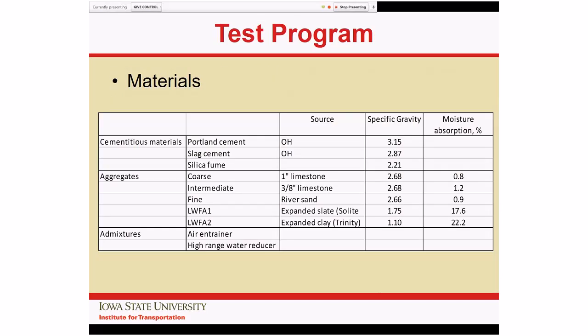All right, so we ran a fairly rigorous program through the lab. We played with Portland cement that we obtained from Ohio and a slag cement from Ohio. We contacted a silica fume supplier. The thought being that if we put a little bit of silica fume into the mixture, we would significantly decrease the permeability of the system, and we wanted to see if we could still get crack-free environments with that. We used Iowa limestone aggregates just to keep the costs of hauling material down, but they were not very different from the materials that you have locally in Cleveland.